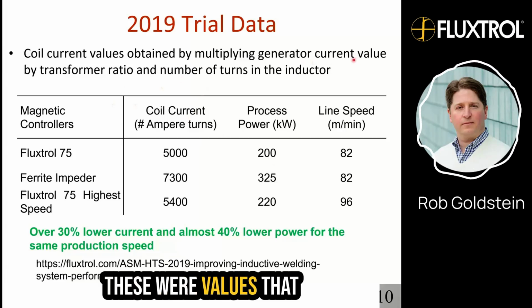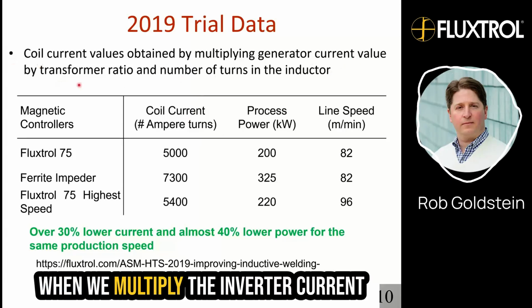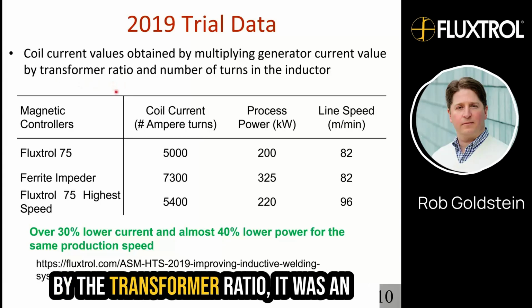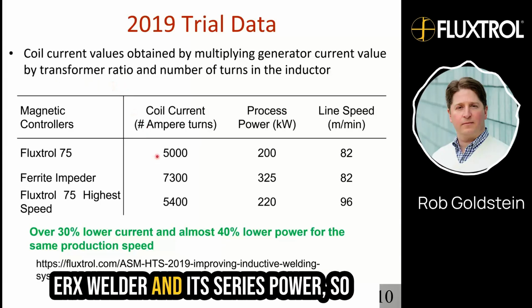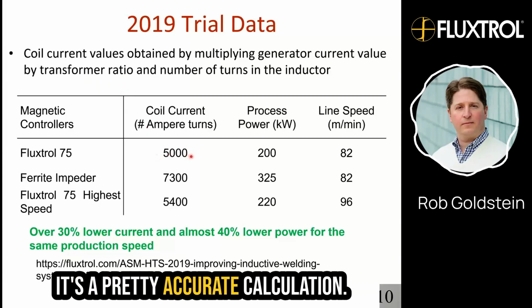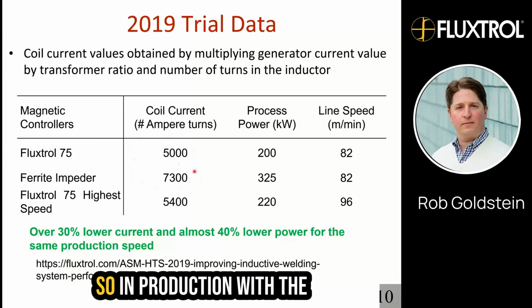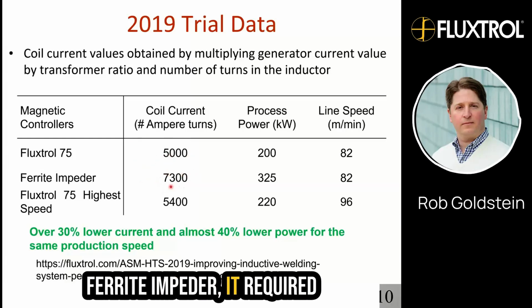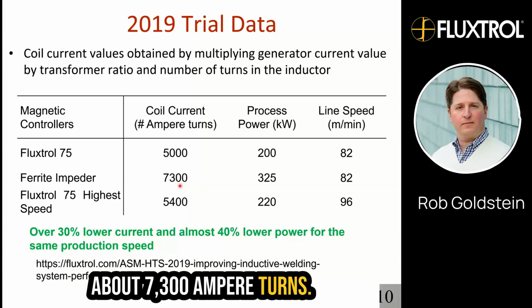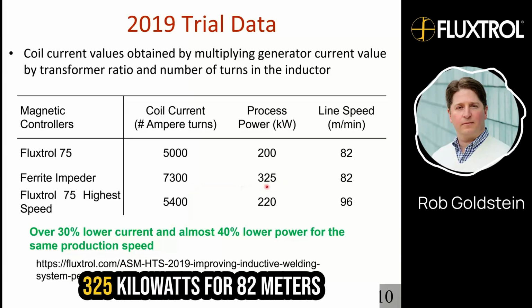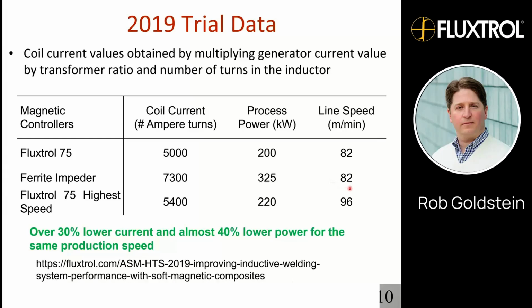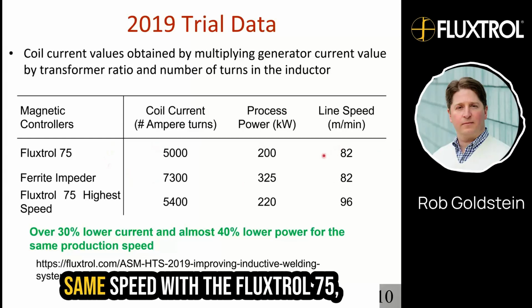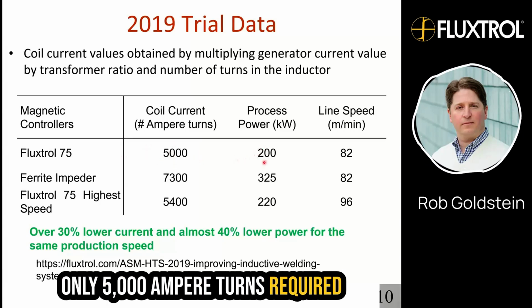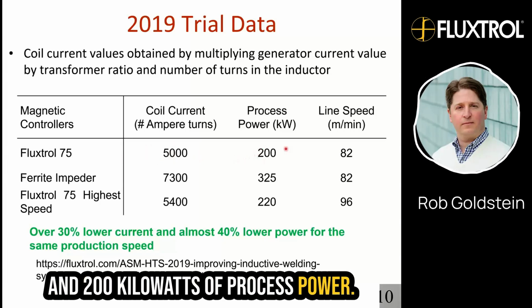These were values that we got off the generator when we multiply the generator current by the transformer ratio. It was an ENRX welder and it's a series power supply, so it's a pretty accurate calculation. So in production with the ferrite impeder, it required about 7,300 ampere turns, and the generator was consuming 325 kilowatts for 82 meters per minute line speed. When we replaced that and went the same speed with the Fluxtrol 75, only 5,000 ampere turns were required and 200 kilowatts of process power.